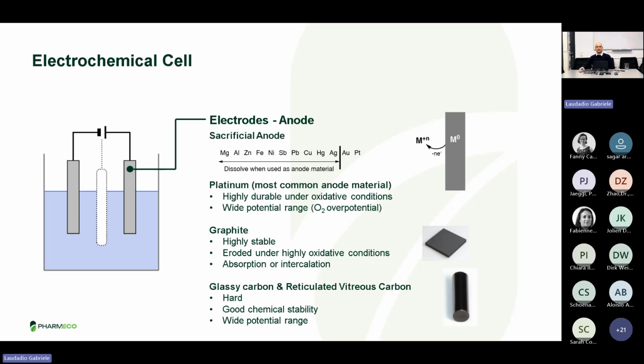Another common material that can be used is the carbon-based electrodes, in particular graphite, which is relatively stable, and extremely inexpensive. However, it can be eroded or corroded in very harsh oxidation conditions. Otherwise, we can use more robust carbon-based materials, which are, for example, glassy carbon or reticulated vitreous carbon, also called RVC. They are usually very hard, robust, sturdy, chemically stable, but they are more expensive.